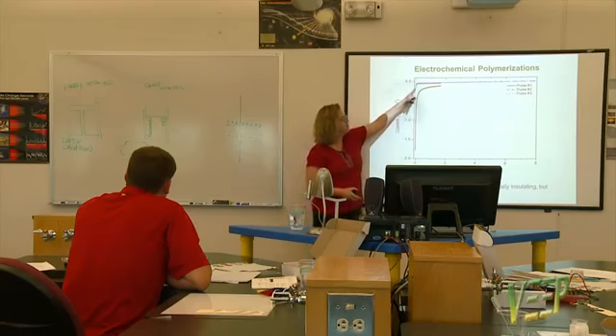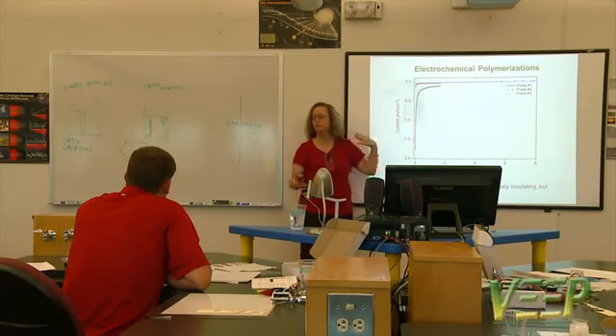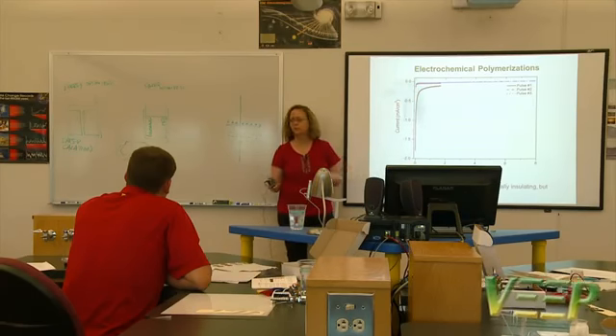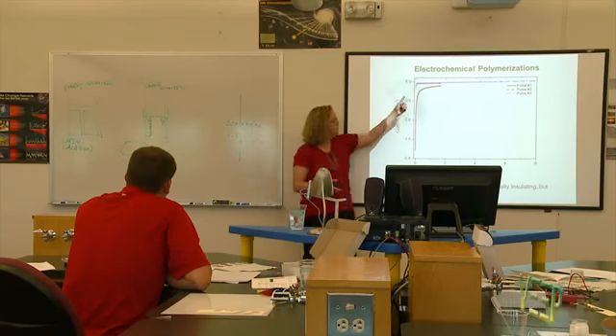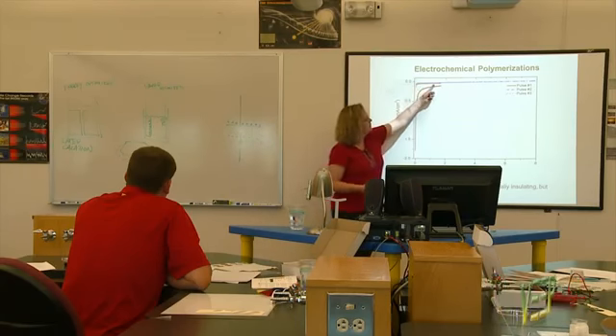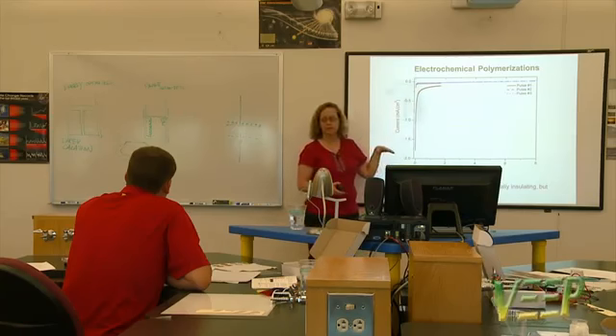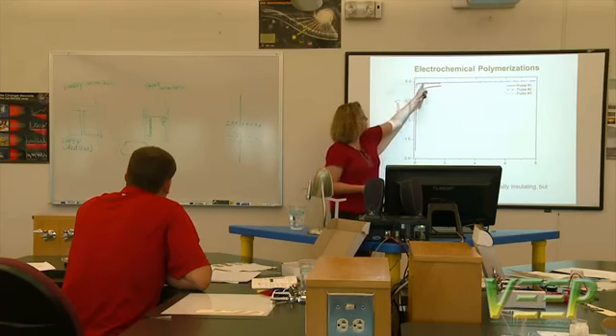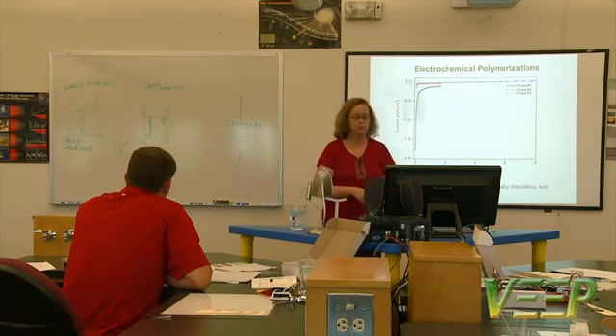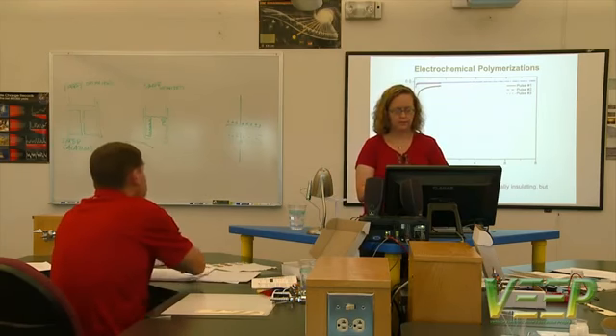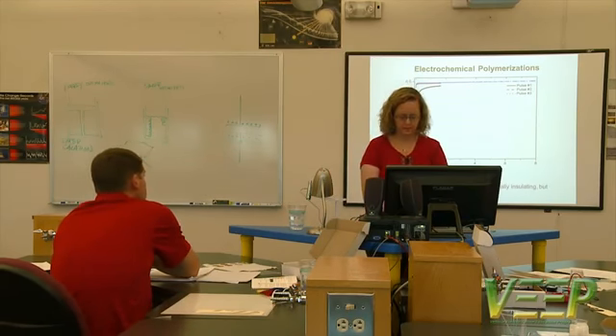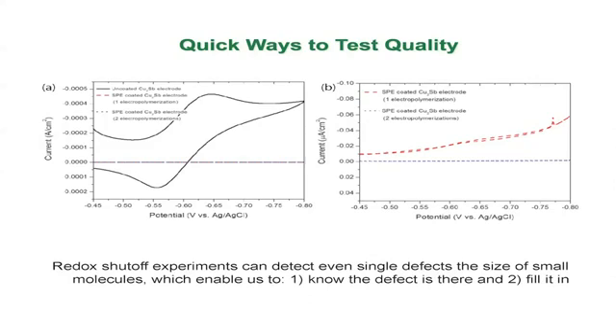The second pulse is in red, and you see that the current started really low because most of that structure was covered already and no more polymer could grow there. So it can only grow where there are bare patches. It approaches zero pretty quickly. Then we let it rest, and then we do a third pulse, and the current's really low. So that tells us it's pretty good, but it doesn't tell us it's perfect.